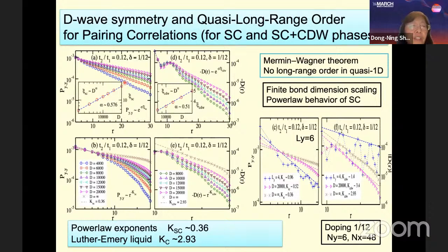For a given bond dimension, the correlation does decay exponentially, but when we scale those correlations to infinite bond dimension, we find the correlation length increases beyond 10, around 50 for the largest bond dimension we used. If we scale the bond dimension to infinity, the correlation length diverges.